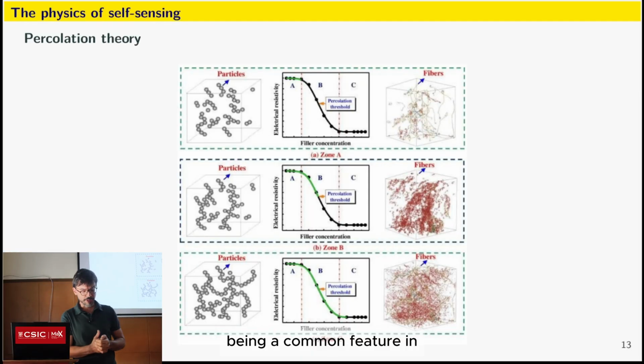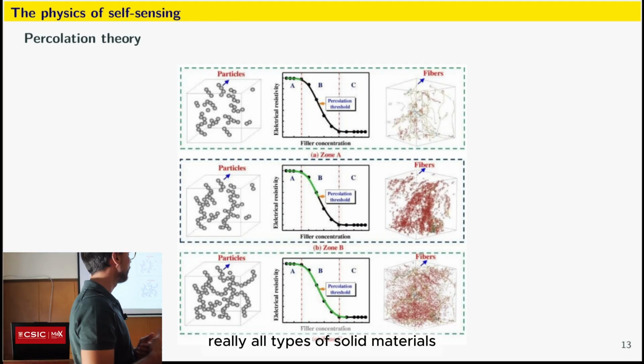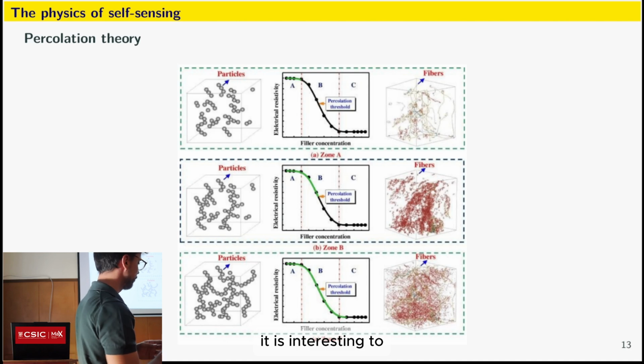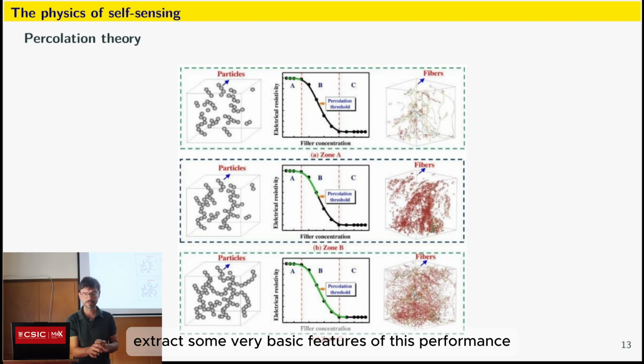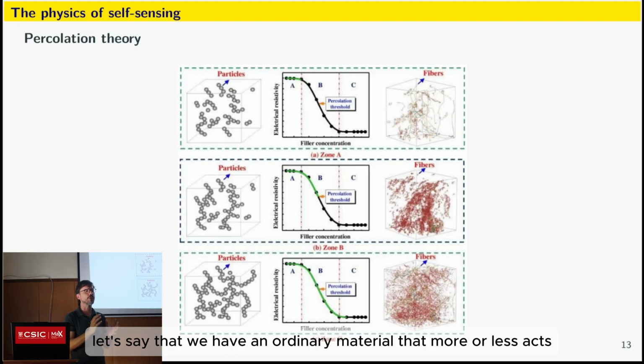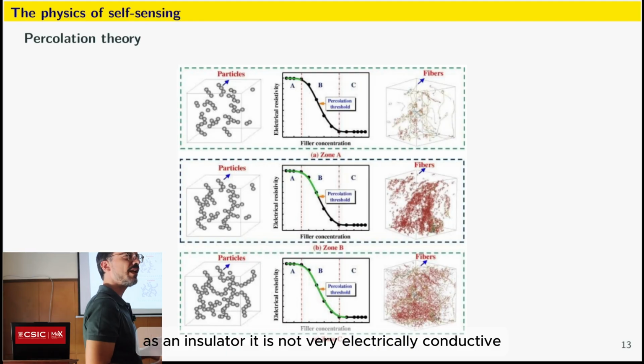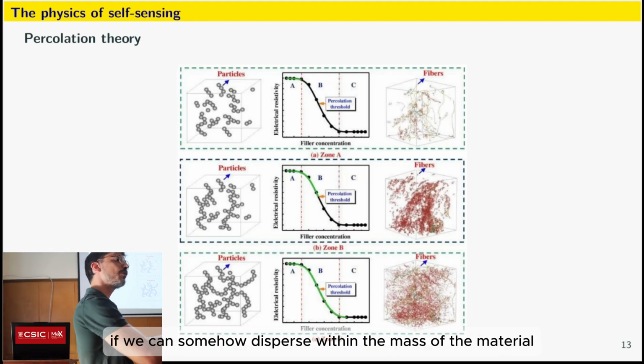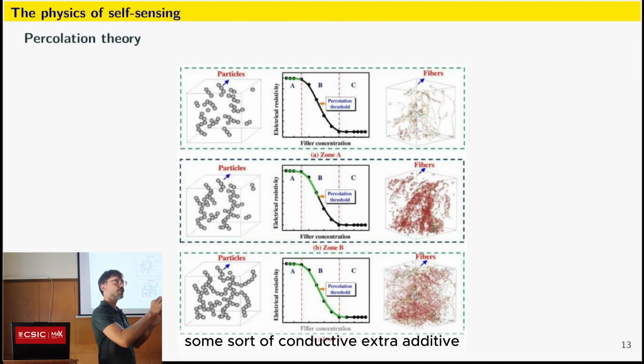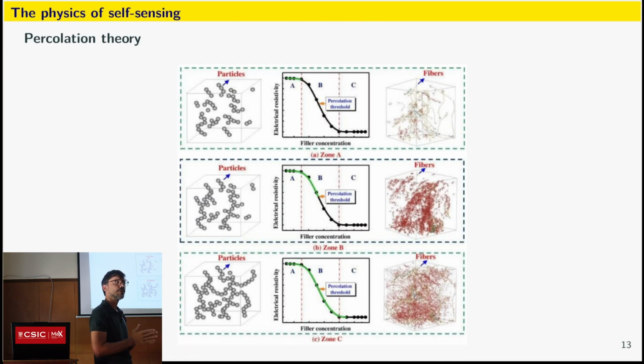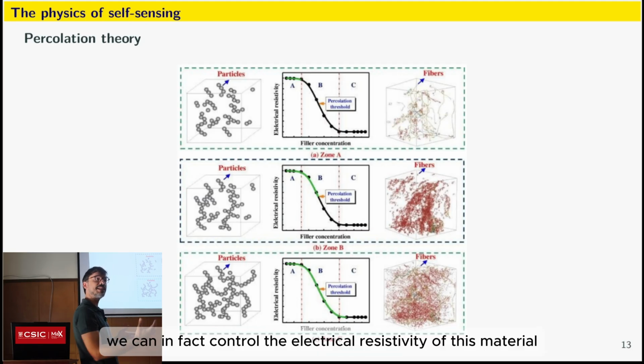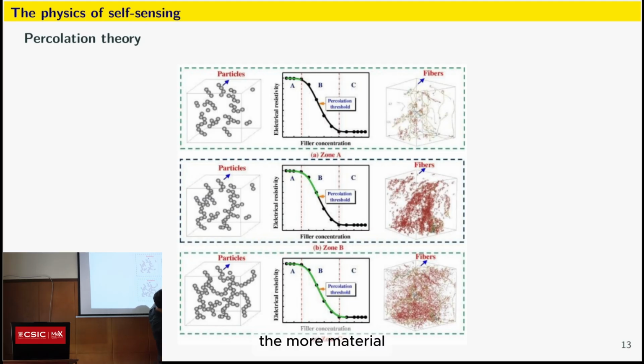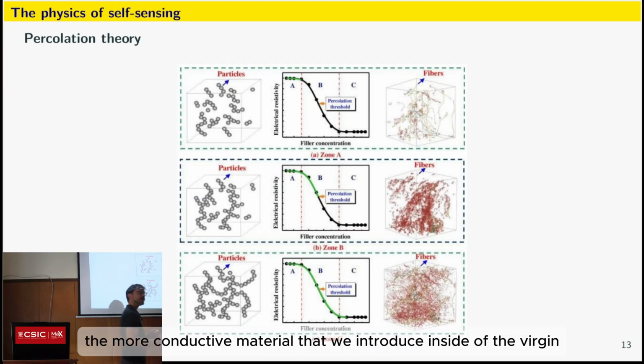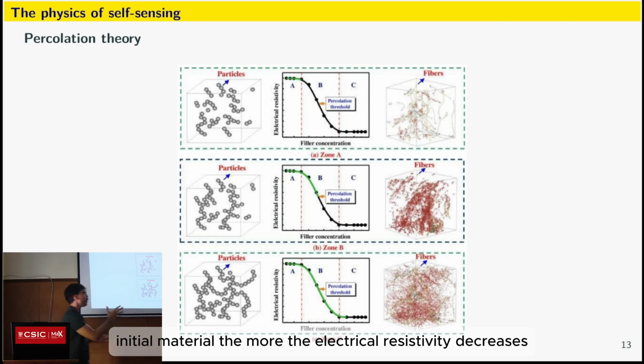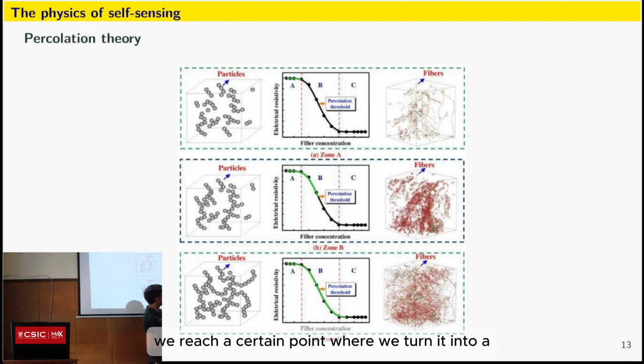Being a common feature in really all types of solid materials, it is interesting to extract some very basic features of this performance. Let's say that we have an ordinary material that more or less acts as an insulator. It is not very electrically conductive. If we can somehow disperse within the mass of the material some sort of conductive additive, we can in fact control the electrical resistivity of this material. The more conductive material that we introduce inside of the virgin initial material, the more the electrical resistivity decreases. And in fact, at the end, we reach a certain point where we turn it into a highly efficient conductor.